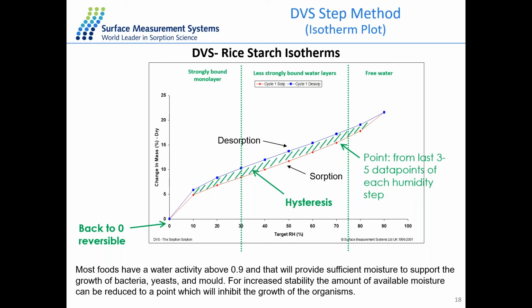The shape of this isotherm is a quite typical type 2 isotherm, widely found for food material, which shows a monolayer region to begin with, and then a multiple layer region for lightly bound water, and then a free water region at higher humidity conditions. The free water is used for the growth of bacteria, yeast, or mold that will destabilize the material. So we can use this water isotherm to optimize the shelf life or the stability of the food products.